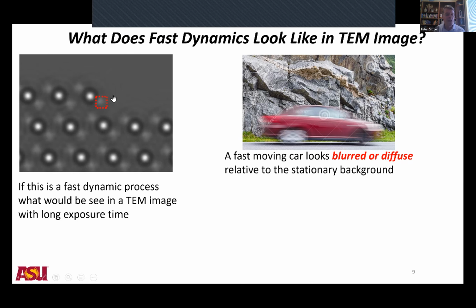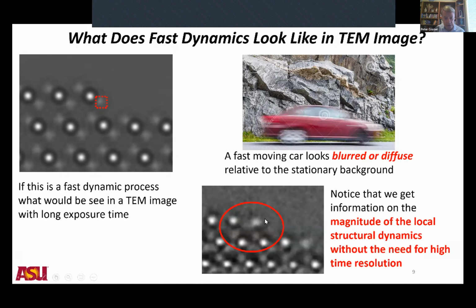And so if we were to image this, we would have a superposition of these kind of images. And I always, to try and explain this, if you think of a fast car moving forward and you take a photograph with a long exposure time, the car, of course, looks blurred or diffuse relative to the background, but of course, you still know that it's a moving car. And so the interpretation that led us to for these fuzzy atomic columns at the step is that, in fact, the reason they look fuzzy is because they're dynamic. They're moving back and forward during the exposure time, and that's causing this fuzziness that we see.